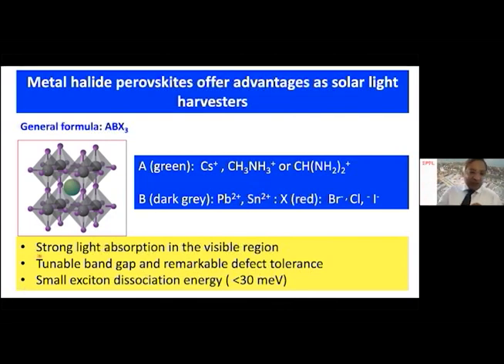I have highlighted only three main properties here. Strong light absorption. What do I mean by strong light absorption? It absorbs the whole visible region from 400 to 800 nanometers. Tunable band gap, this topic we have discussed already. We can tune the band gap by changing the halides, by changing the B cation, changing the A cation. Then the small exciton dissociation energy.